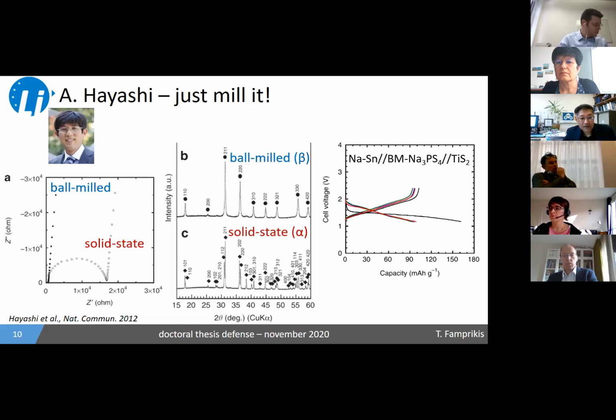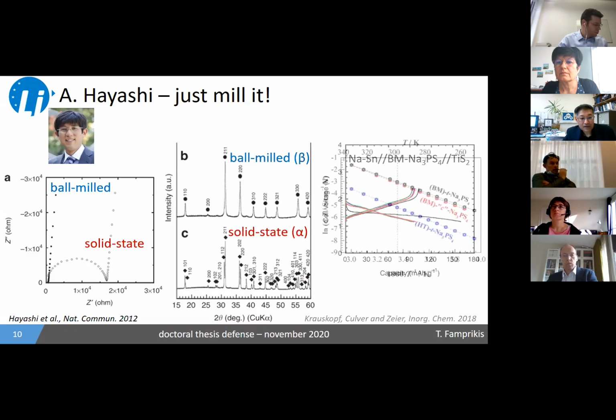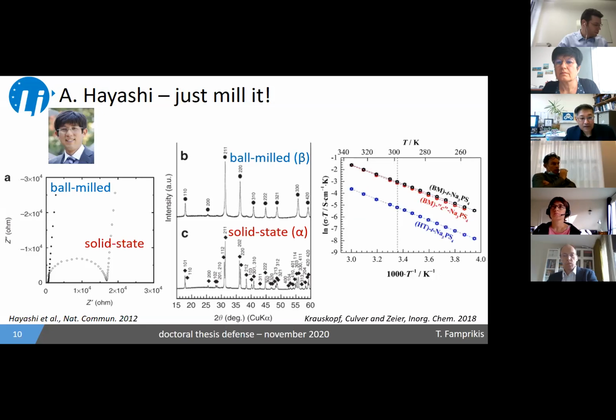And this whole effect of the ionic conductivity enhancement has been reproduced multiple times in the literature, at least 10, 15 papers. I'm just showing here an example from the group of Zeier, where you can again observe the 1 order of magnitude increase upon ball milling the material.